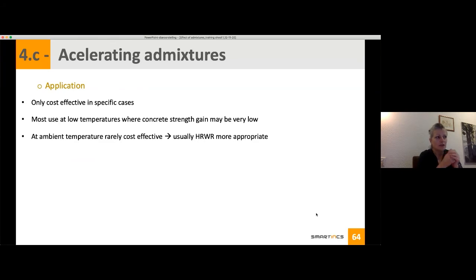Accelerators are not that widely used compared to the other admixtures, and that comes also from cost effectiveness. They can be used at low temperature, because then you need a really fast strength development. But otherwise, at normal temperature, usually you will use a superplasticizer instead of an accelerating admixture. And then you also have the positive effect on your workability and on your dispersion.